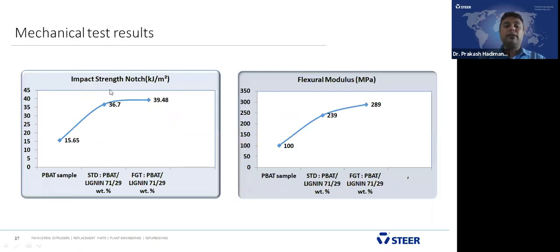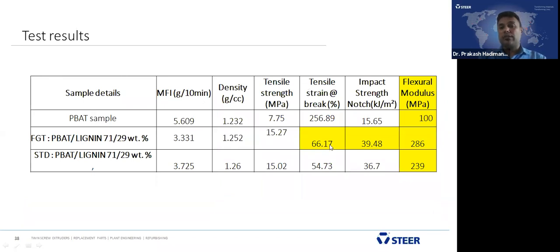For mechanical properties, we compare the standard versus FGT. The standard shows an impact strength of 36.7 kilojoules per meter square, and FGT with the same combination provides 39.48. In flexural modulus, the addition of lignin increases it, and compared to the standard, FGT gives the best results: FGT 286 megapascal versus the standard 239. Comparing both, FGT gives better impact strength and flexural modulus compared to our standard technology.